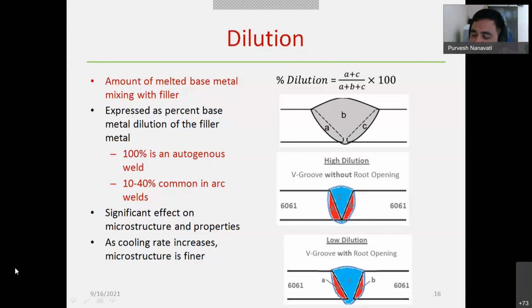So this dilution has a significant effect on the microstructure and the properties. Look at the two figures below. In the middle figure, the joining of 6061 aluminum, you can see this is a V groove without root opening. So there will be a higher dilution from the base metal, right? Now you see the third figure, a V groove with root opening. You see most of the time the blue color. This means the weld metal composition will be more like the filler metal composition. So it will be mostly undiluted filler metal composition, or the weld metal chemistry will be very near to the filler metal composition.